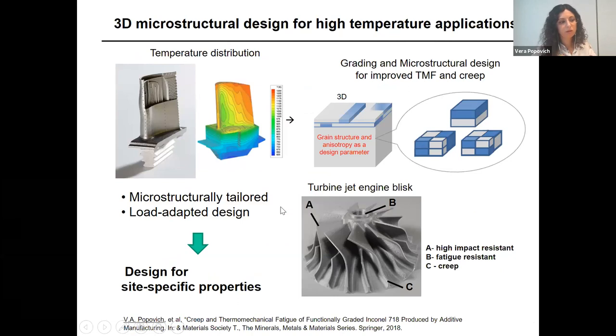of properties and performance. So what is our approach? It's not only ours, but we were the first ones, five to six years ago, that developed this, and now more and more groups and companies pick this approach up. It is to start not from the material approach, but from the approach of a component. So what are the boundary conditions that are imposed on the component? What is the temperature distribution? What is the stress distribution? And with respect to this, what type of material properties would you like to have, for example, on the tip of the blade, on the base of the blade, on the core structure? And they could be different.